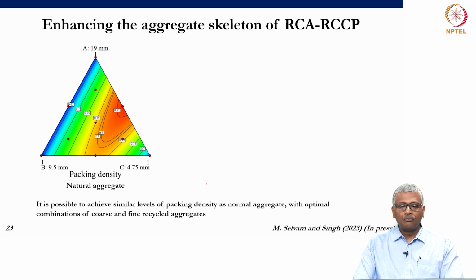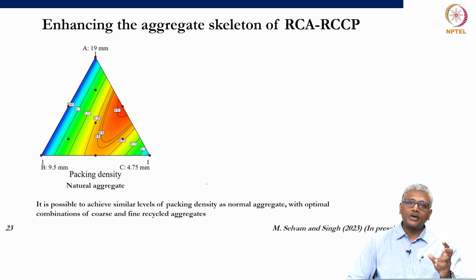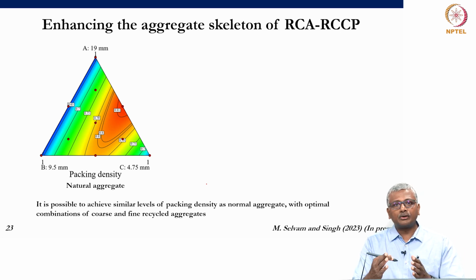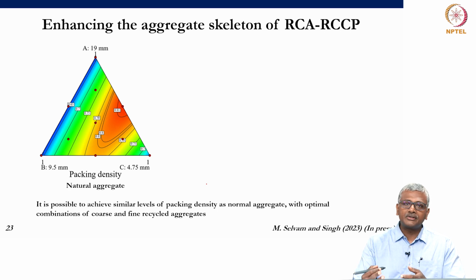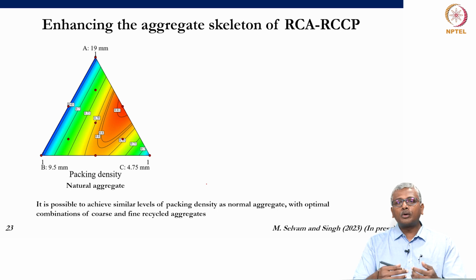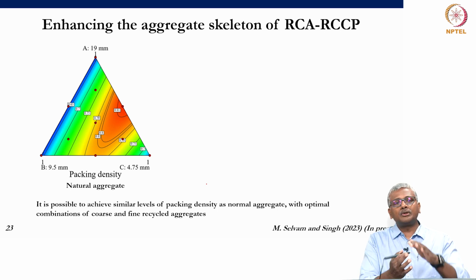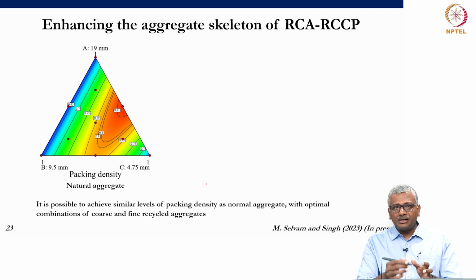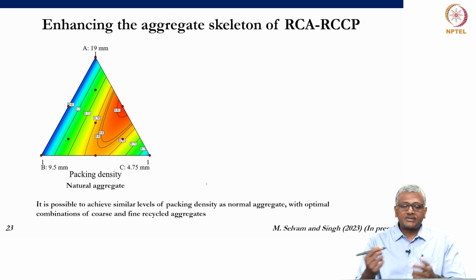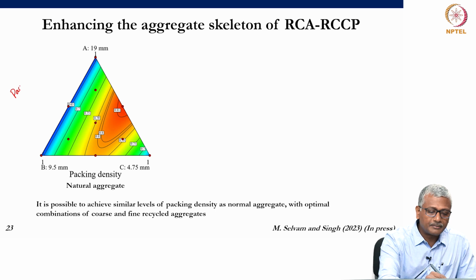So, now what we can try to do is design the roller compacted concrete pavement with an optimal choice of your gradation of your aggregate, right. We typically work with coarse aggregate of two sizes, 20 millimeters, 12 millimeters, and then one fine aggregate which is less than 4.75 mm. So, now you have three different materials that need to be blended or proportioned in a way that can give you the maximum compaction, and that generally can be achieved by maximizing what is known as the packing density of the aggregate.